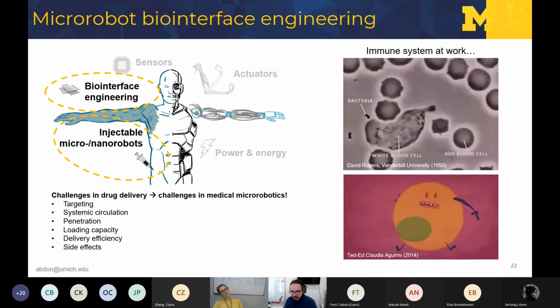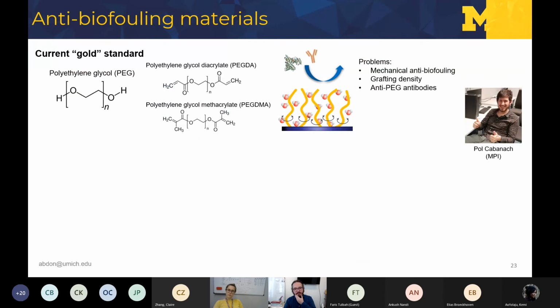So we're very interested in this problem, especially because at the root of this immune recognition, there is a biofouling problem, and most people use PEG as a gold standard anti-biofouling material to prevent the non-specific absorption of plasma proteins, for example. And this is great, and it works okay, but it has some problems, right? So the anti-biofouling properties of PEG rely on a good grafting density. They rely on mechanical agitation, and we're starting to see already some anti-PEG antibodies, right? So they work good, but not great, right? So this limits a lot the protection of these PEG coatings for immune recognition and immune clearance and absorption of proteins.